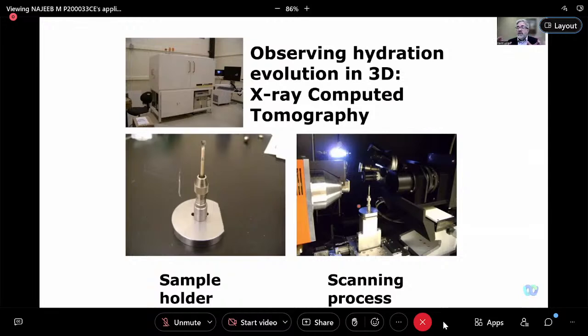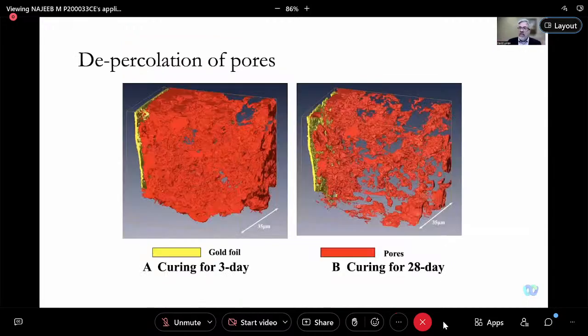Now you take 180 images and throw them in a computer and ask the question, what was in the middle of that sample that explains simultaneously all those 180 images from the different angles? It does that hard problem, and it comes up with a picture that shows you the three-dimensional reality of density in your sample. We did some where we were creating an interface with a gold foil, and you can see two pictures, one after 3 days, one after 28 days, where we found a way to take our sample and ensure alignment of the orientation so that we could get a match of the images at 3 days and 28 days. That was part of what we were trying to do.